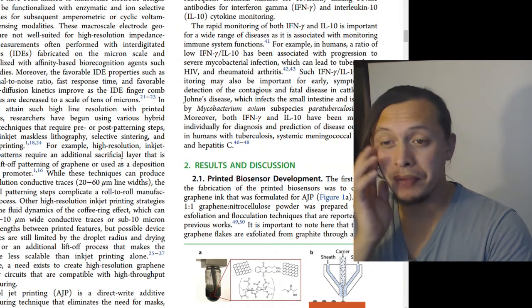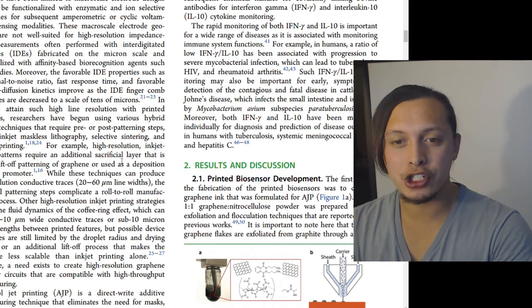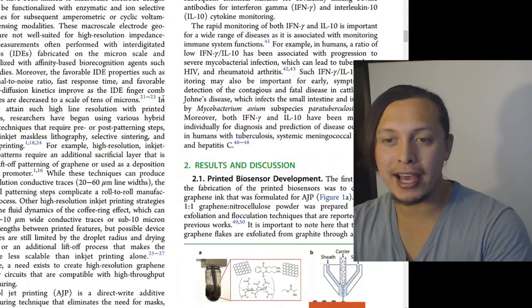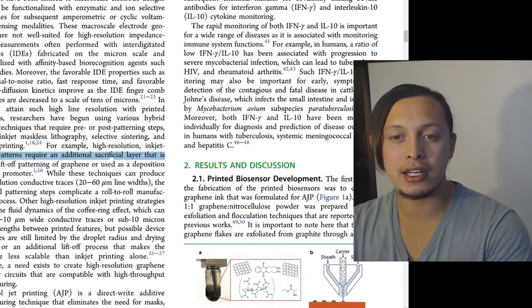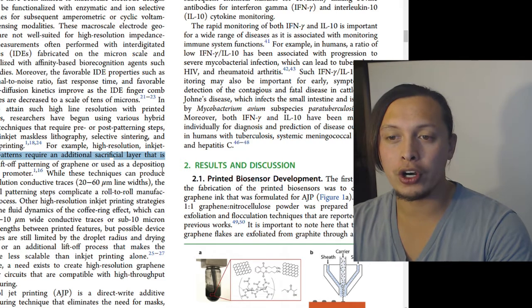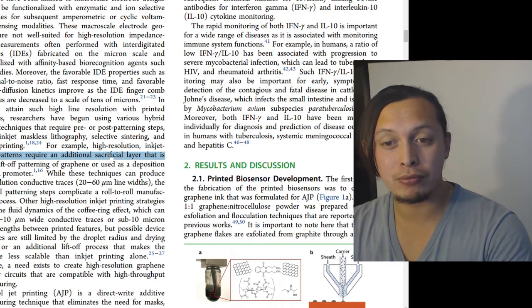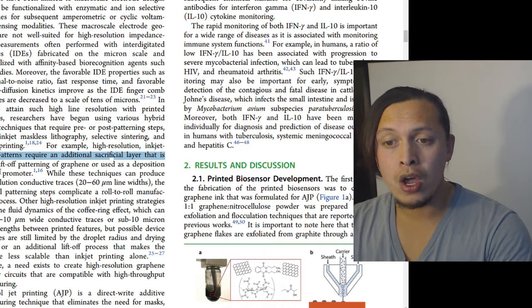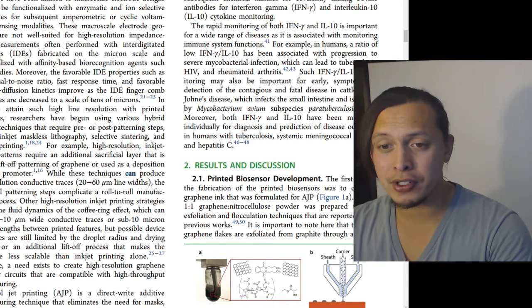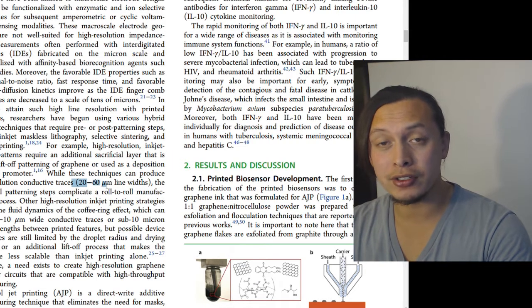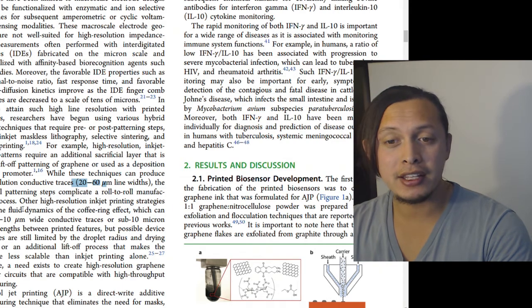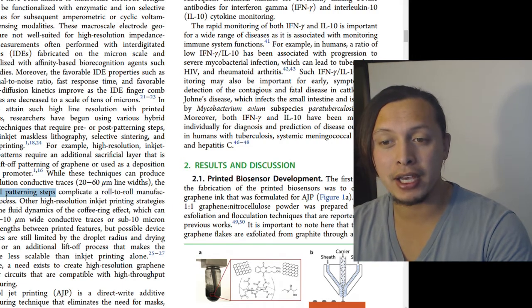So for example, high-resolution inkjet printed patterns require an additional sacrificial layer that is used in a lift-off patterning of graphene or used as a deposition adhesion promoter. While these techniques can produce high-resolution conductive traces, so 20 to 60 micrometer line widths, the additional patterning steps complicate a roll-to-roll manufacturing process.